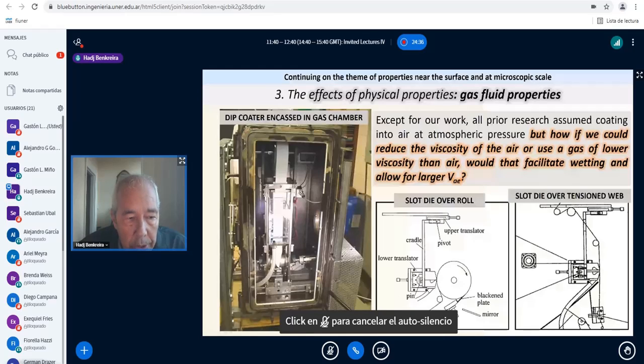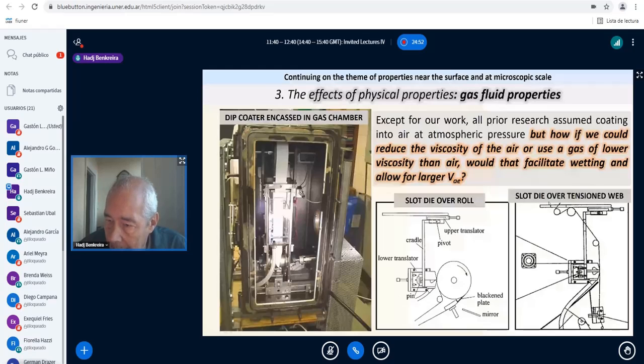But we not only used the dip coater, as you see in here, but also we inserted a slot coater, a slot die over roll, like you see in here. This is the slot, and this is the roller. Or we also inserted the slot die over tension web, which is essentially the same slot die, but instead of driving the substrate around the roller, we drove the substrate between two rollers, so we have it tensed around the slot. So this is why it is called slot die over tension web. And then our proposition was, what are we going to observe? Are we going to decrease or increase the velocity of air entrainment? As we propose, we say this is what should happen. So let's see at the data.